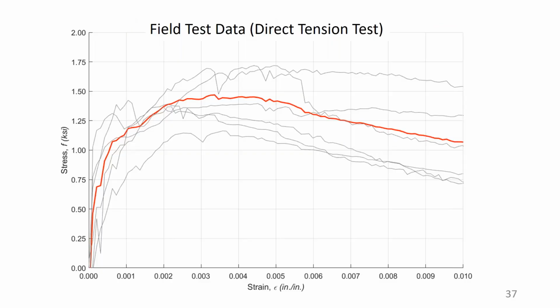Basically what I'm showing here are the tensile results. For me, I was pretty impressed to see this. In fact, the localization strain was higher than what we achieved in the lab, and I'm not sure how to explain that. The tensile strength was lower. Remember, it was 1.82 KSI in the lab. Here it was closer to 1.4 something, 1.5. The localization strain was about 5 to 10% more. But the other thing that I see is that there's more variability. I'd accept that because of the way the specimens were made and because these are field specimens.